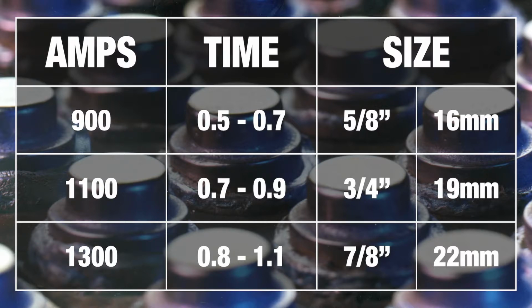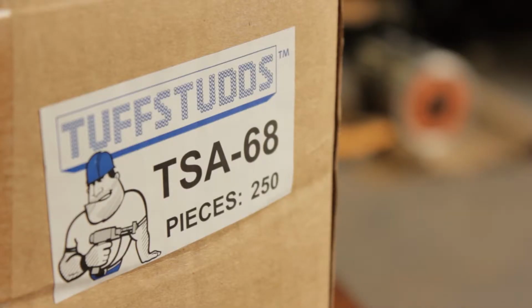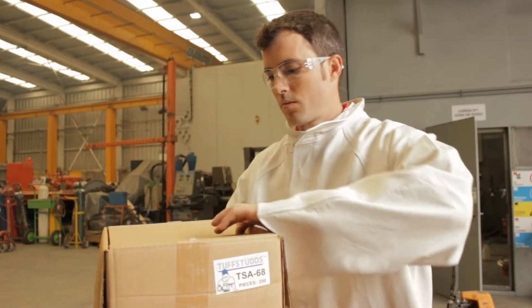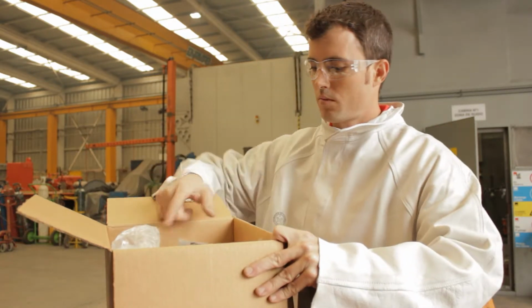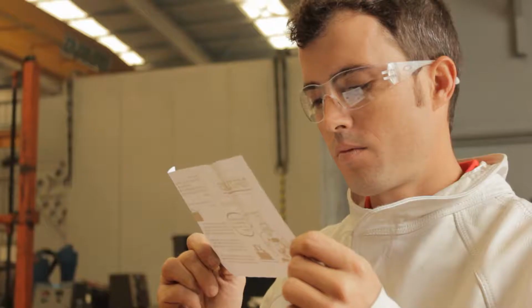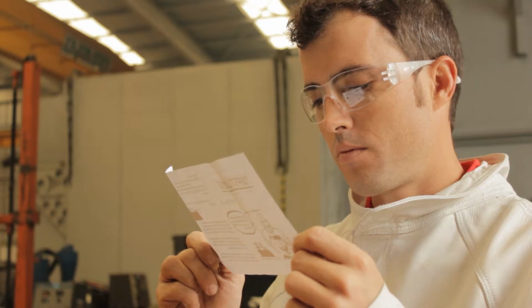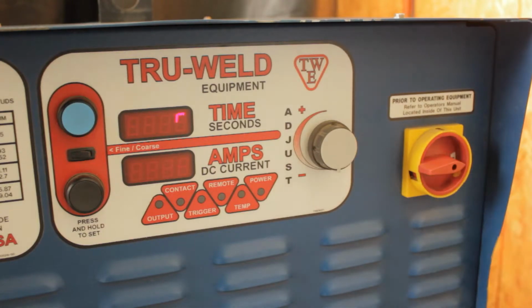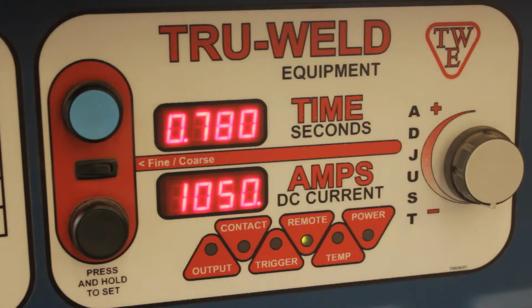3/4 inch TuffStudds about 1100 amps and between 7 and 9/10 of a second. 7/8 inch TuffStudds about 1300 amps and between 8/10 and 1 and 1/10 of a second. Every box of TuffStudds has an insert showing the range of amperage and time for that particular stud. Always start at the midpoint of range. Both the amperage and time length settings mentioned are a starting point for the first welds.